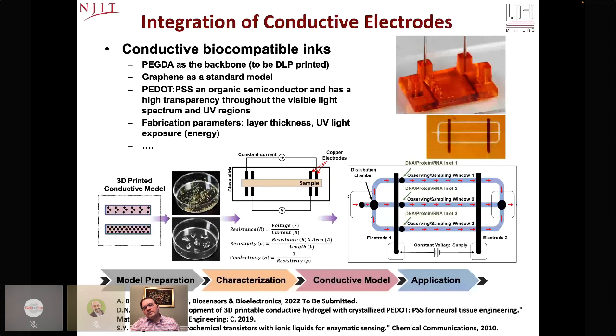Another thing that we were interested in is that for microtissue, you need an additional component, which is making conductive electrodes out of the hydrogels, so we can 3D print a microfluidic hydrogel-based device while there are some electrodes already built in the whole process. You are not going to do it as an additional process. It is going to be built in, for example, in the chamber. And again, we started using the same backbone material, which is PEGDA in our case.